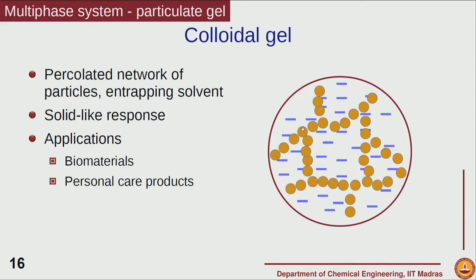Because of the overall cross-links the material has an overall rigidity and is therefore called a gel. Similarly, in a colloidal gel we have chains of particles where the chain itself is not completely rigid, giving a soft solid nature due to the flexibility of these chains. Colloidal gels differ from macromolecular gels in that these cross-linking points are physical — like a physical macromolecular gel — so the cross-link points can also form and break. Therefore, the colloidal gel response will be quite soft solid-like, with the largest relaxation time being high but also the presence of several smaller relaxation times.